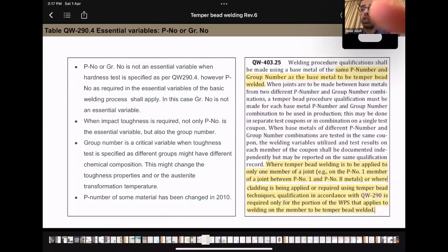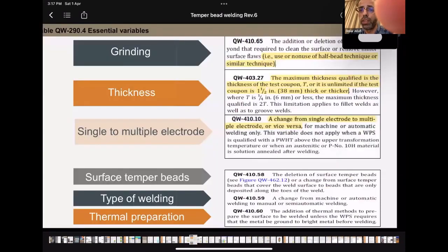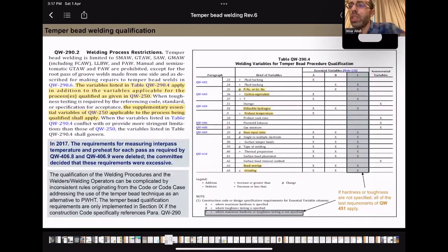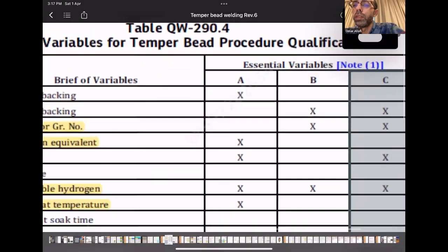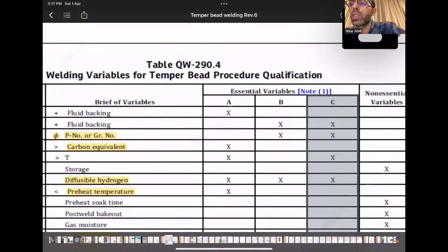P number. So I'll just go quickly and refer to this table. As you can see here, P number and group number is only an essential variable when toughness is required, for column B, when toughness is required, and it is not required for hardness. So does that mean that when hardness is specified for temper bead, the P number is not a factor? I mean, does that mean that if I qualify P22 material, I can use the same WPS for P11 and carbon half moly and normal carbon steel?